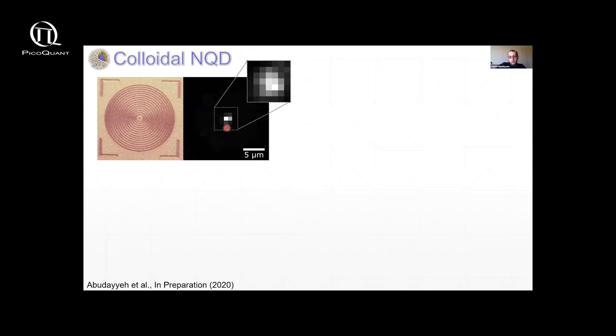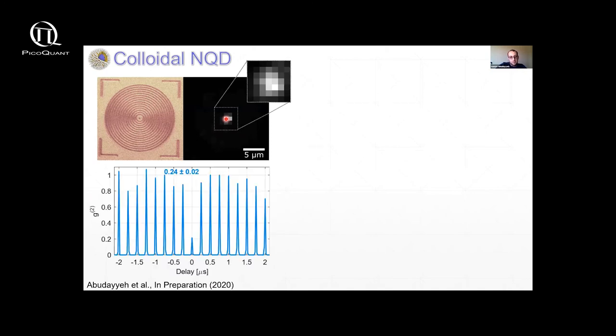So what you see here, again, is this microscope image and a fluorescent. This is actually a confocal fluorescence image showing that there's only emission from the center of the device, indicating that we've selectively bound these quantum dots actually only to the nanocone and nowhere else.